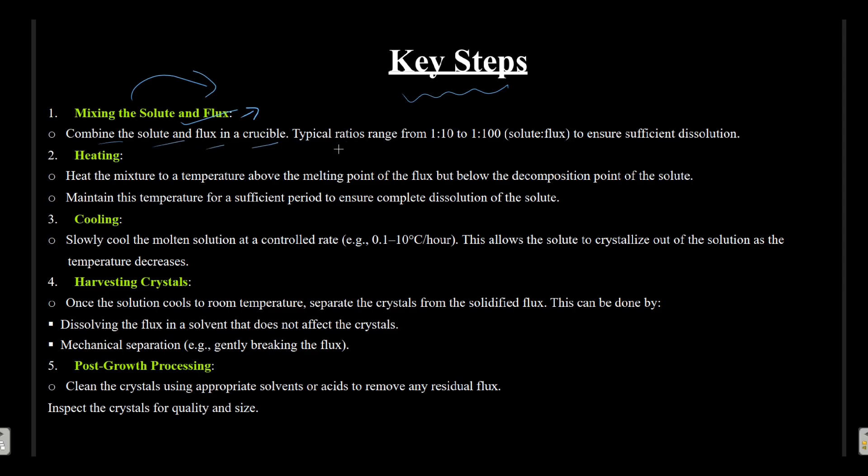Typical ratios range from 1:10 to 1:100. That means the flux should be taken in a large amount, the solute should be taken in a small amount, to ensure sufficient dissolution.